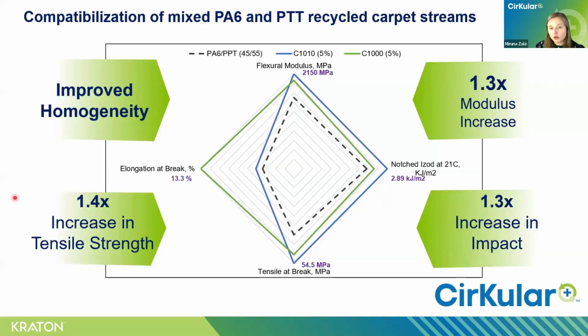So as we mentioned before, our goal was to enhance the homogeneity and mechanical performance of this PA6 and PTT blend. And in this graph, we are showing in dotted gray line the baseline performance, which was the PA6 PTT blend in 45 to 55% ratio. And then in blue, it's the performance when we add C1010 at 5%.